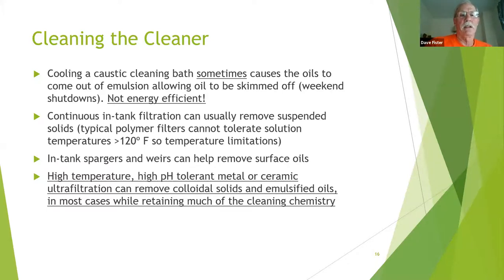One way to get an oil emulsion to break is you cool the bath down, and I'll say sometimes that allows that emulsion to form an oil layer and get skimmed off. So basically a weekend shutdown to let the tank cool down. Not energy efficient, because now you're cooling the tank, or allowing the tank to cool, and have to heat it up at the beginning of the week.